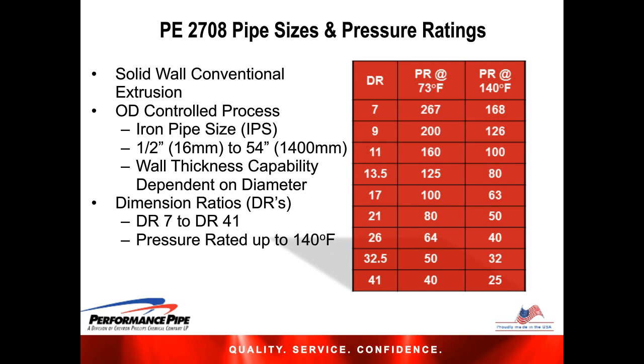The wall thickness capability for this new product is generally limited to around 2 1/4 inches. However, that is dependent on the diameter of the pipe. Basically, smaller diameter heavy wall pipes have more heat in the pipe than a larger diameter pipe. The bigger pipes have more surface area than smaller pipes, so the heat dissipates faster, resulting in less slump. So we can do heavier walls in bigger pipes than we can in smaller pipes. So please check with your distributor or pricing coordinator to determine the manufacturing capabilities to meet your requirements.